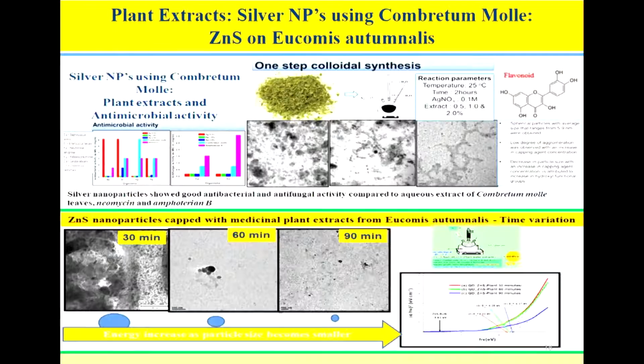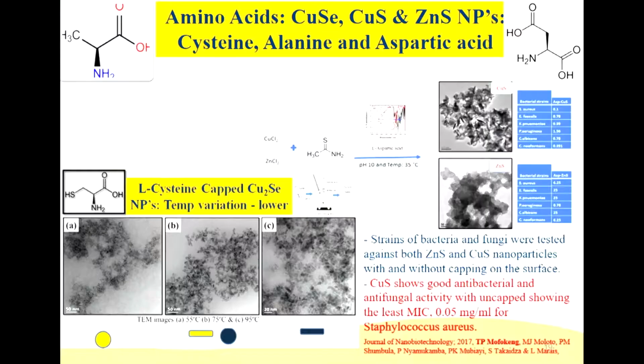As compared to starch and other chemical molecules that I've done before, you can see that the control is not better, but as you increase the amount of the flavonoids, the amount of extracts, the particles become much smaller, which is the opposite of the trend you would normally observe in other scenarios. The same happens when you increase the time, where the particles become smaller and smaller as you allow them to interact with the plant extracts.